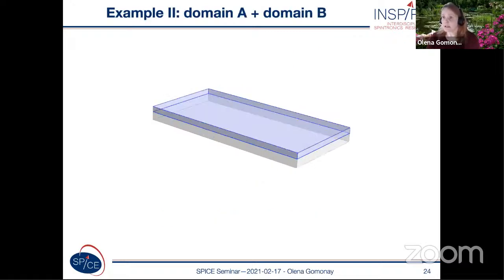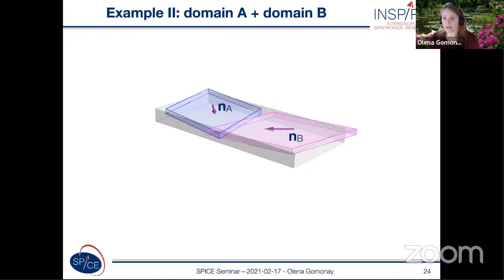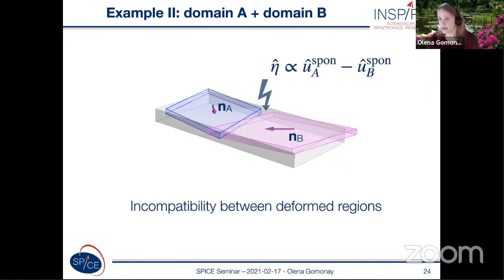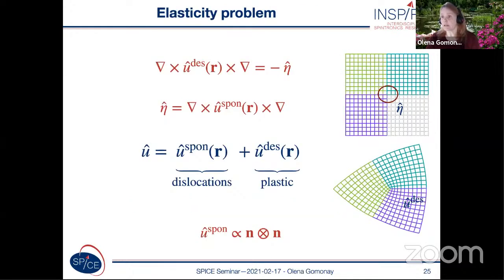Another example can be given by an antiferromagnet with different magnetic domains. So these domains could be deformed in a different way. And at an arbitrary interface between these domains, we can again find that the strains do not fit each other and create incompatibility between deformed regions. So this incompatibility seems to be an intuitive concept, but in elasticity theory, it has a very accurate definition through mathematical symbols. And in fact, this incompatibility is a tensorial analog of the curl of a vector.